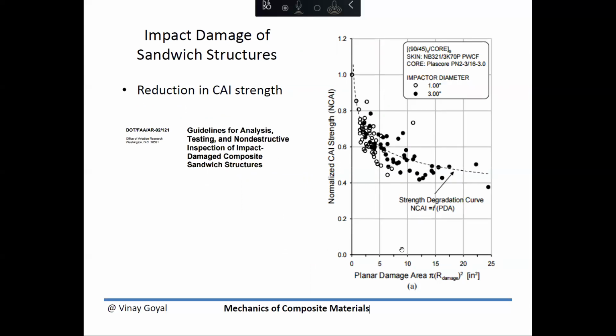You can see here that the more the damage is, the lower the compression after impact strength you get. What I am talking about here is if you have a plate and you subject it to an impact event, when I apply loading in compression, how much load can I get relative to something that was not impacted? So 1.0 is no damage. And then when you apply damage, how much strength reduction do I get because of this type of damage event? You can see here that the damage events can cause degradations in the order of 40-50%.